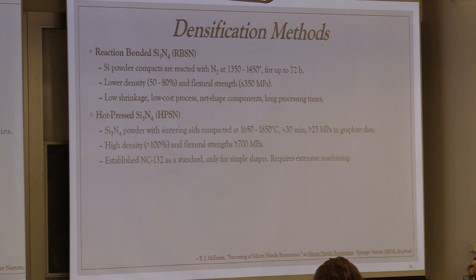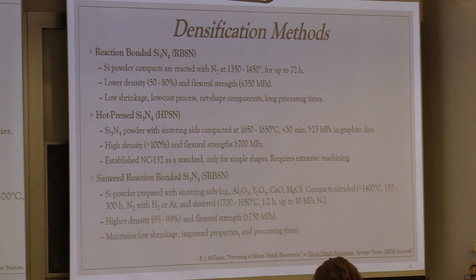The first method that was used is called reaction-bonded silicon nitride. You form a compact of silicon, and then you nitride the silicon compact to form a device. It has very low shrinkage, but also reasonably high porosity and very low strength. It produces nearly net-shaped components, so it's good for refractories, and that's what it was originally used for.